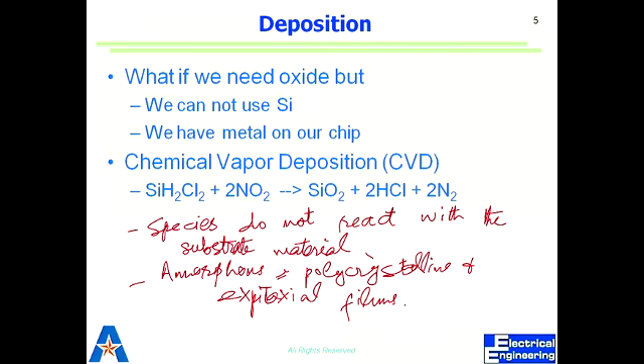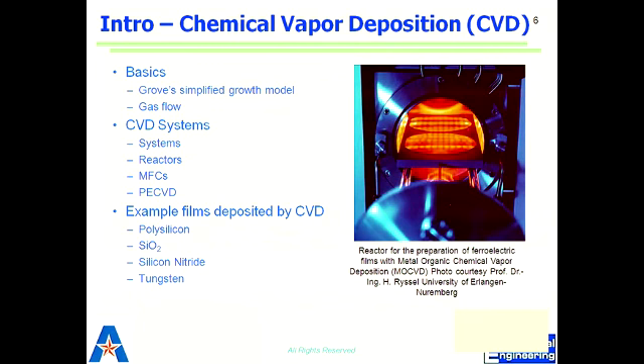How thin does the layer need to be? All you need is a monolayer, maybe several monolayers; different materials need different thickness. Generally it's about 10 nanometers. If you want to cover everything, it has to be at least 100 nanometers, but it depends on the material. So we can't just deposit gold and expect it to stick. Yeah, it will come out very easily in the next cleaning process. That was just one example. There are many different combinations of what we use in our deposition to make sure that it sticks.